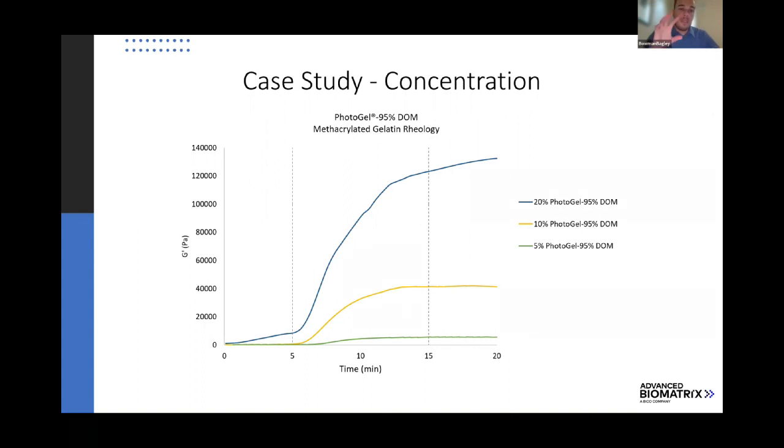And keep in mind with rheology, my rheology results are going to be different than your rheology results, which is kind of funny to say in science. But rheology is so dependent on testing methodology. Are you using a machine that uses vibrations or lasers? Are you pulling the sample? Are you straining, twisting, compressing, stretching?